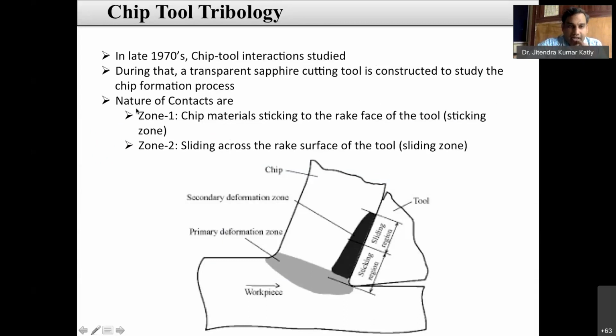He observed that the chip material is sticking to the rake surface. First it sticks because of the high temperature, and because of the high speed it slides after some time. Due to this sticking, then sliding happens. So with sticking and sliding, the material is diffused over the chip and the tool material. That's why the crater wear is always away from the nose, because the nose temperature is very high. So here you can't get a crater wear, but it is a little away from the nose of your cutting edge. This is the reason: the sticking region, then the sliding region.